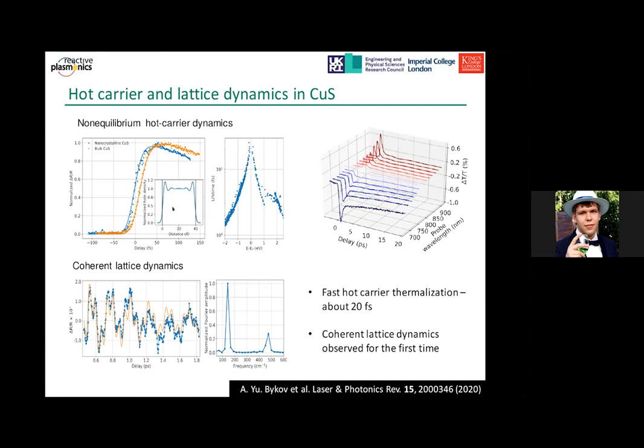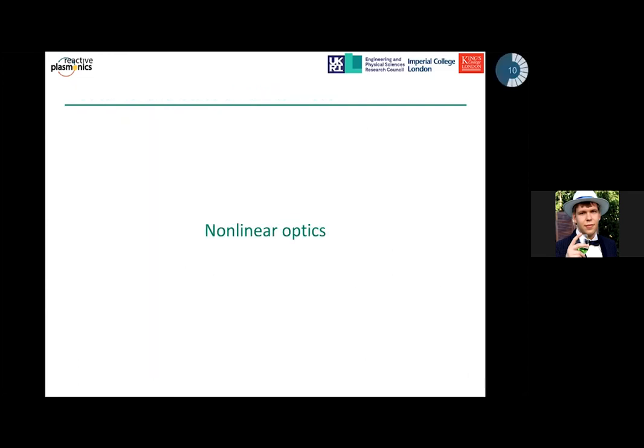An unexpected result of this research was that we also were able to observe for the first time the excitation of coherent lattice dynamics, which are two different optical phonon modes excited coherently in the material, and which can also be advantageous both for fundamental study of electron-phonon interaction as well as coherent control, for example. The last part of my talk will be devoted to nonlinear optics.